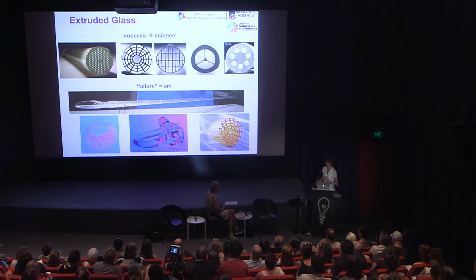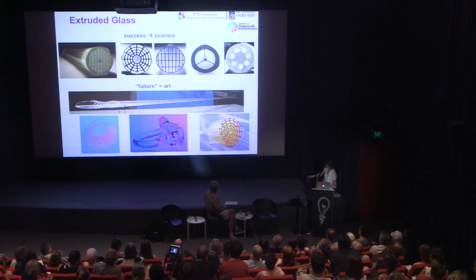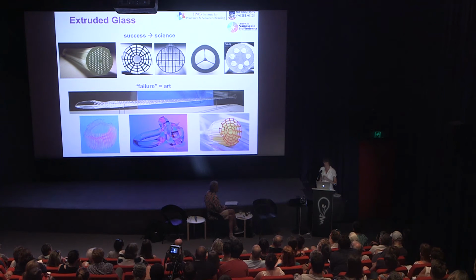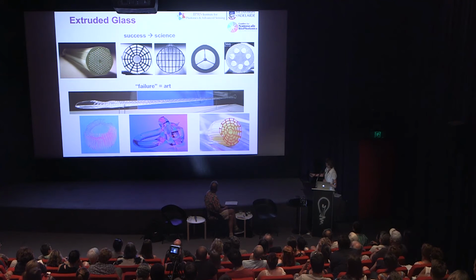And so this is our sphere. There was something obviously wrong with the flow behavior when the glass was flowing through the die, which caused stick-slip behavior. That's not really useful to make an optical fiber, but it looks good. With this one, the furnace profile was not even, so there was a cold place in the furnace, and therefore when the piece came out of the die, it just bent toward the cold part of the furnace, and then it started to coil up. And here the holes look very regular, but it looked a little bit different to what I wanted to achieve according to the die design.